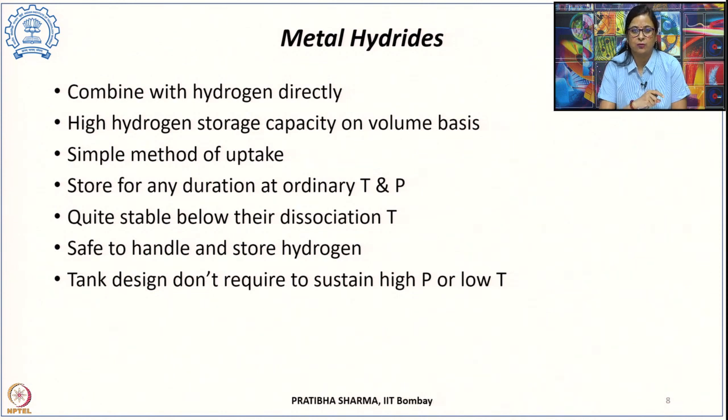But unlike the liquid state storage, when the storage was carried out at 20 Kelvin, here the temperatures involved are not that low. At the same time, the metal hydrides are very much stable. They can be stored for much longer durations, and they are quite stable below their dissociation temperature. Important thing here is that until the temperature is raised, or let us say if there has been a leak in a metal hydride based storage system, the reaction of release of hydrogen is endothermic. Because of that, a self-cooling effect may arise, and that will further reduce the temperature of the metal hydride because of the endothermicity of the reaction, and that will stall the release of hydrogen. So, it is very safe to handle and store hydrogen.